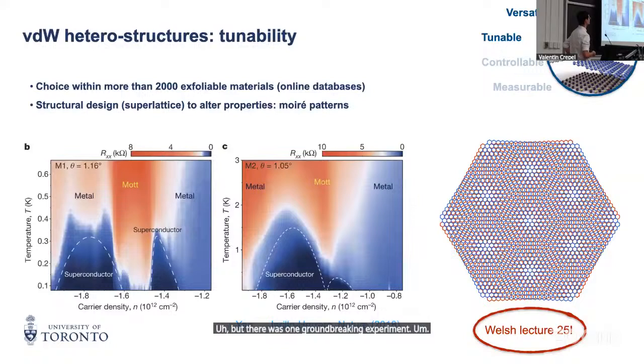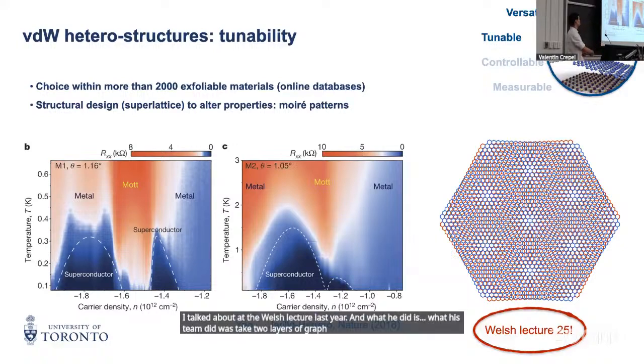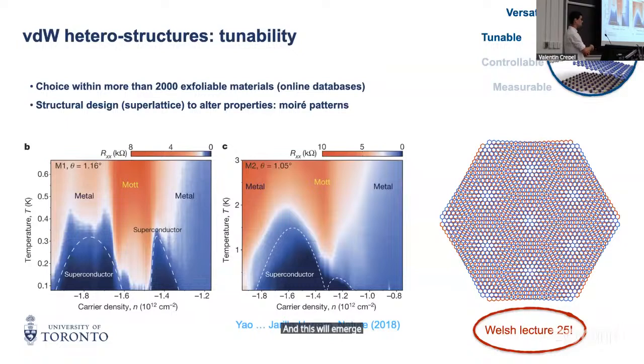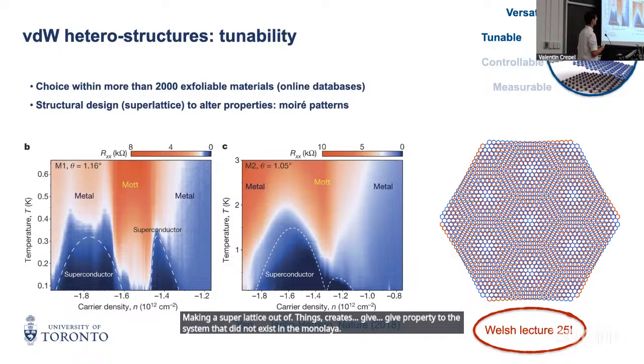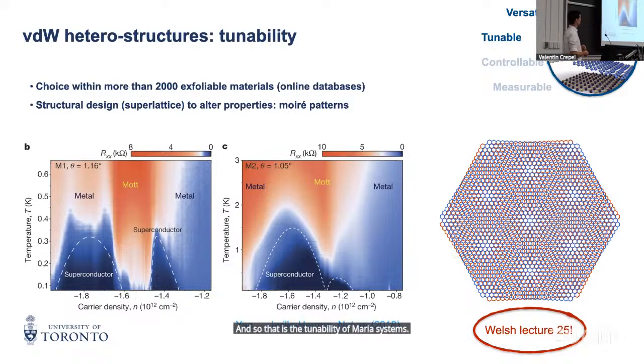So that doesn't mean that it's useful for any purposes, but there was one groundbreaking experiment in 2018 in the field that shows that those interference patterns are actually good for something, and that they can promote new physics in your bilayer that did not exist in the monolayer. So that's probably what Pablo Jarillo-Herrero talked about at the Welsh lecture last year. What his team did was take 2 layers of graphene, twist them by about 1 degree, and they saw a superconductor emerge, while none of the graphene sheets by itself is superconducting. So again, making a superlattice out of things gives properties to the system that did not exist in the monolayer. And so that is the tunability of moiré systems, right?